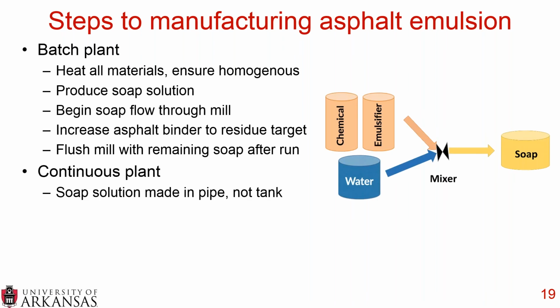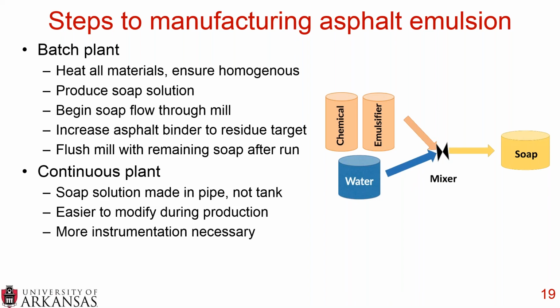A continuous plant's a little different. Instead of making the soap solution in a tank, you make it in the pipe and you make it on the fly. So you have your chemical, your emulsifier, and your water. You add those all together in a pipe and it goes through a static mixer, and that makes the soap solution. And if you do this in a batch plant, it goes into a tank. If you do it in a continuous plant, it goes into the pipe and then directly into the mill. So you don't actually have a tank of soap solution in a continuous plant.